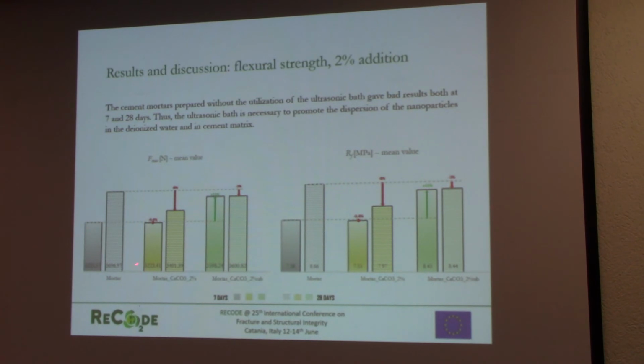And this is the first result because probably we need, and probably in the industrial plants, there will be need the solidification of all the mixture. What is interesting is the difference in terms of 7 and 28 days, because as you can see, at 7 days, the mixture with the ultrasonic bath presents quite an interesting increase in terms of flexural strength, while at 28 days this increase is totally lost. Probably these nanoparticles behave like accelerant particles, and probably they promote an early age strength.